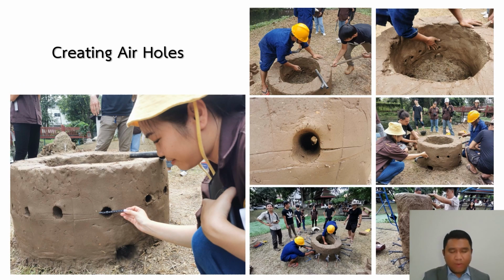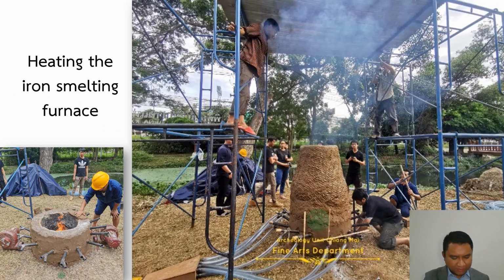Next, making the blowing holes. The team drilled the blowing holes 20 cm higher from the base of the furnace and drilled them into cone-shaped holes. At an angle of 30 degrees to the furnace wall, a total of 16 channels are arranged around the furnace. At the bottom of the furnace, square holes are drilled in the 4 directions.